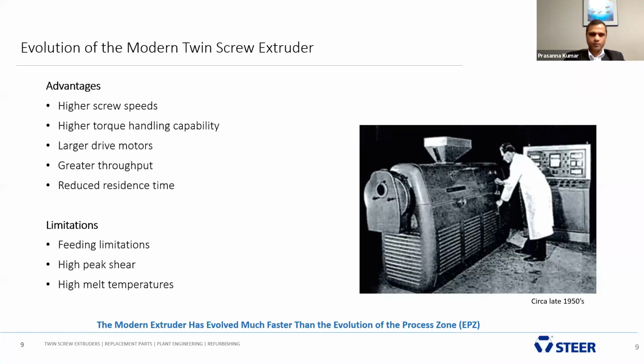Some of the limitations that we have mentioned here are feed limitation for very low bulk density material. There is also higher peak shear because of higher screw RPM. The peak shear also increases and thus results in higher melt temperature as well.